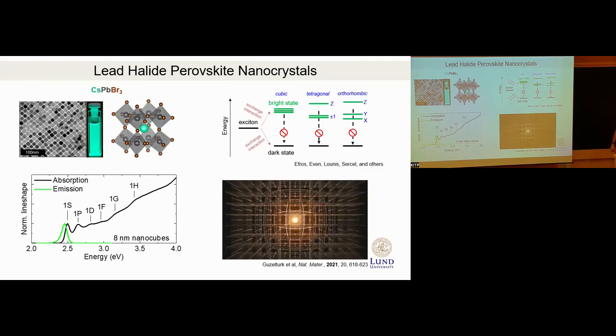And the second reason is polarons. These are ionic semiconductors, not covalent semiconductors, so when you form an exciton, an electron-hole pair, it polarizes its environment, and this sort of protects it from defects. That's the reason why thin film perovskites have very long exciton diffusion lengths, and you can make efficient solar cells.